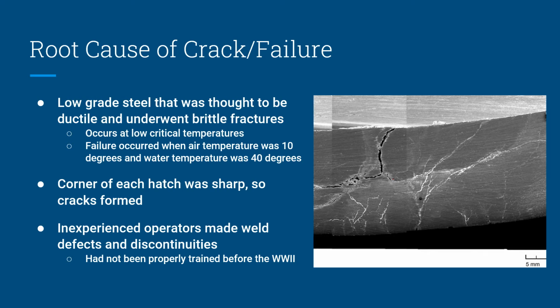The cracks on the ship most likely propagated from the sharp hatch edges around the ship, where the cracks formed and then moved throughout the low-grade steel. We could also conclude that the inexperienced operators who made the welding defects and discontinuities could have had something to do with the failure because they had not been properly trained before World War II.